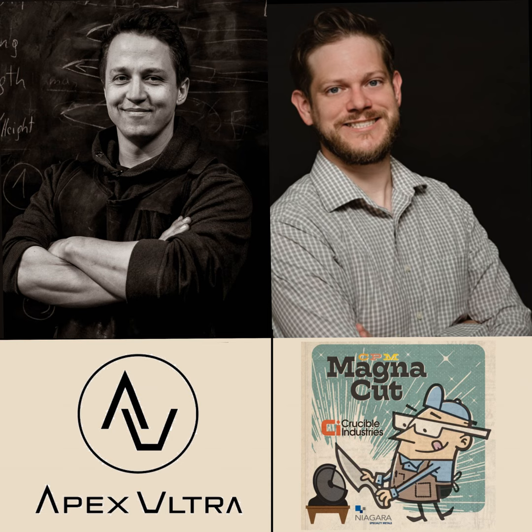This is never going to be zero unless you grind off after hot rolling, which would reduce the yield a lot, and I don't think that's worth it because costs go up, yields go down, and as soon as you throw the piece of steel in the forge, there's going to be decarb in the forge anyways again. So yeah, that wouldn't make sense.